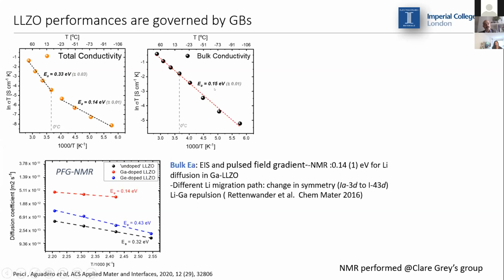Initially, we doubted ourselves, so we did some PFG NMR measurements in order to confirm that actually the value of activation energy was the same, and we see that we've got a value confirmed with NMR of 0.14 electron volts. So this means that our lithium moves very freely and very easily in the bulk of the LLZO.